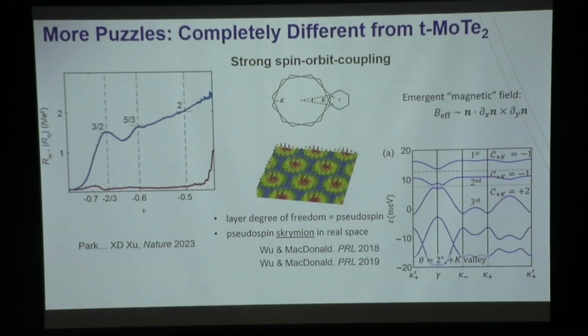And you may be aware of the other material that was discovered last year, in the same year. We have two systems showing fractional quantum anomalous Hall effect. The other system is twisted MoTe2. That system shows two fractions at that time, and that system is just very different from this graphene-hBN Moiré system in every sense that people think matters. In twisted MoTe2, there's very strong spin-orbit coupling, and there is the so-called layer pseudospin degree of freedom that forms skyrmion patterns in real space, and there's effectively an emergent magnetic field due to all these. Well, graphene doesn't have any of those.